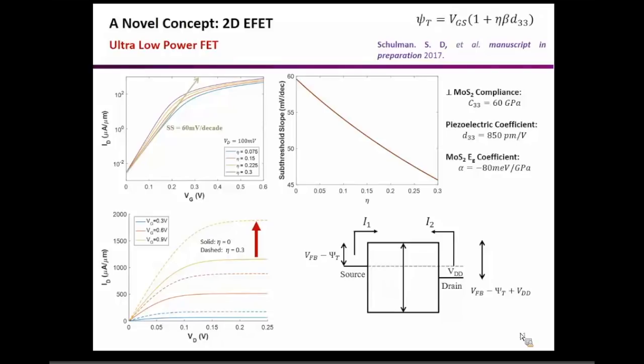You can clearly see that depending upon the strain transfer efficiency, one of the parameters that we are varying, we can actually get down to a subthreshold slope of less than 60 millivolt per decade. Now, I must articulate that the amount of amplification that we get in this device actually depends upon all three parameters.